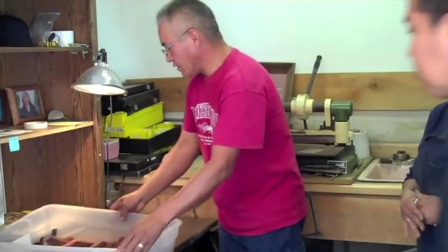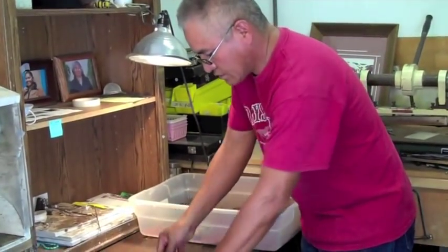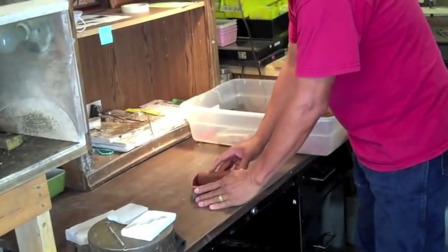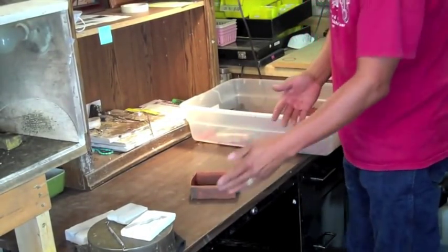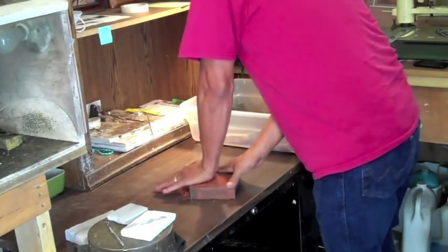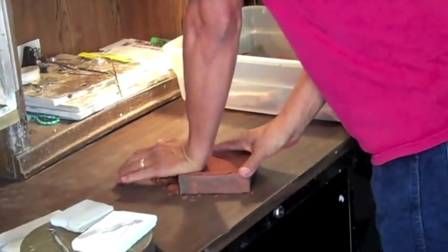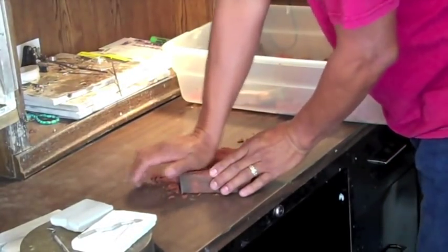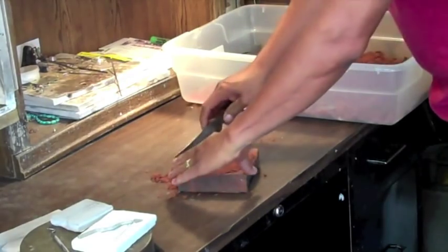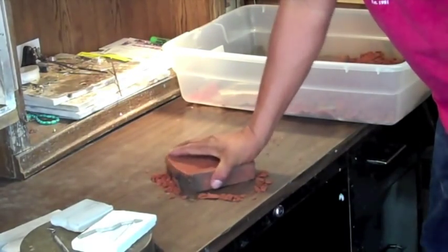Now what I'm doing here is I would put a wooden frame with a little piece in front of it. Let me use this. Is that okay? Set that down, and I would set a sample down that was already made like this. Put the sand down inside the frame and pack it without moving the sample around. I'd have to pack it nice and hard to get the sand in and around the sample, and whatever imperfection it does have when it comes out can be taken care of through filing and buffing and cutting it off with the coping saw.